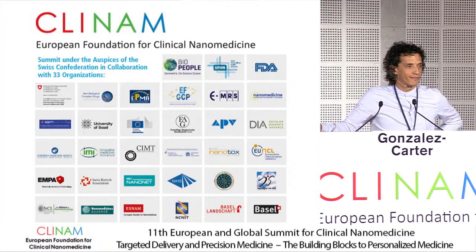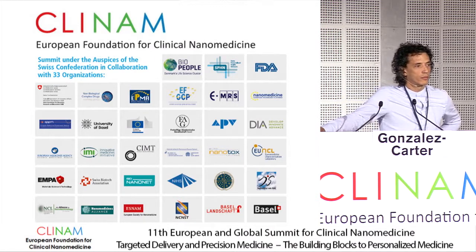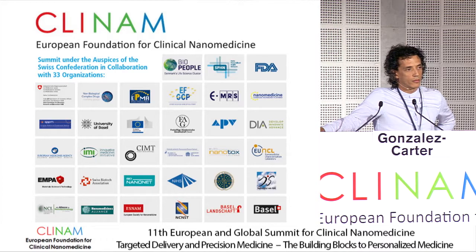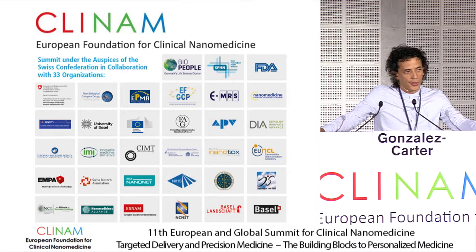Thank you very much, Professor McGee. Thank you for your talk. I just have a technical question. How do you do the correction for the fluorescent content in the brain? Because you have a Cy5, which is in the core of the micelle. So when you go into the endothelium, you're going to be in endolysosomes. So when you consider the volume of the vesicle and the moisture content, you are going to disrupt your liposome. It's not going to be at the CMC level. You're going to be well below the CMC level. So technically, your monomers are released. So the micelle gives you quenching, yet when you have the free chains, you get an enormous amount of fluorescence. So how do you do the correction in terms of what is really in the brain?